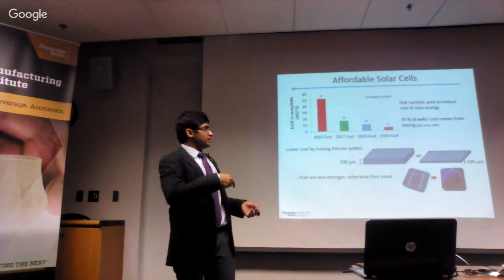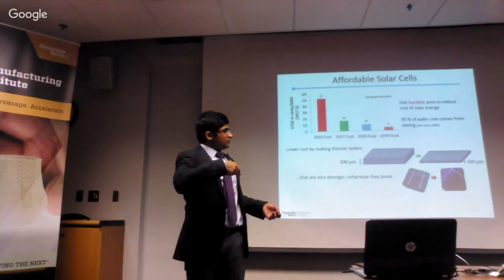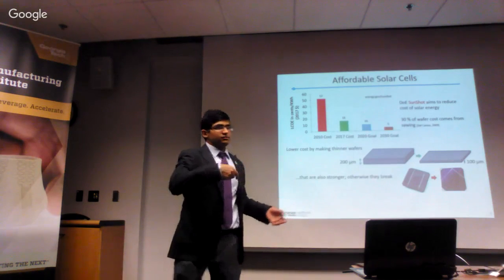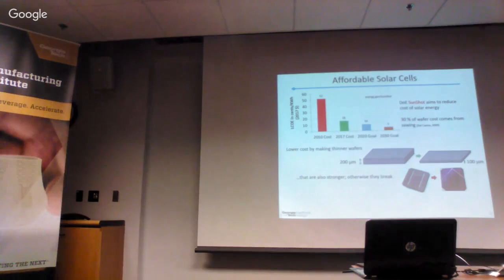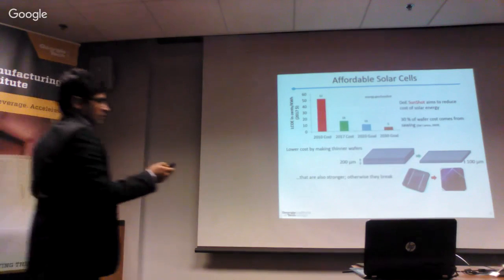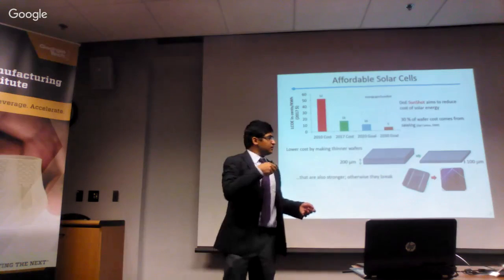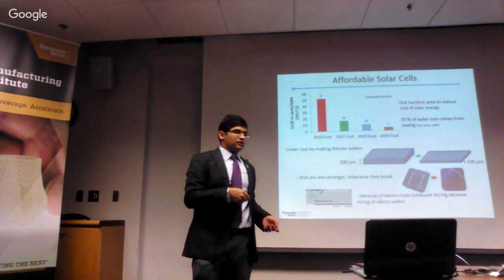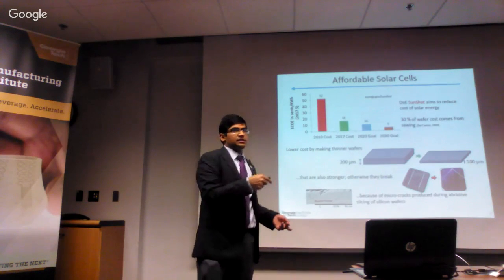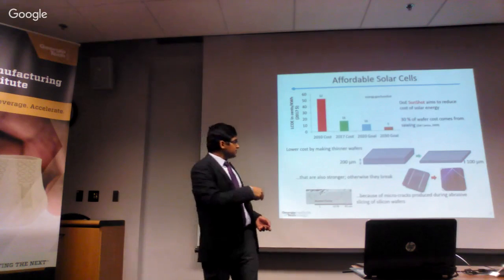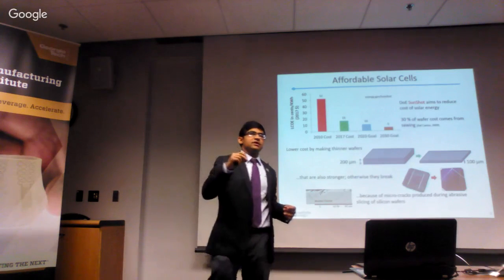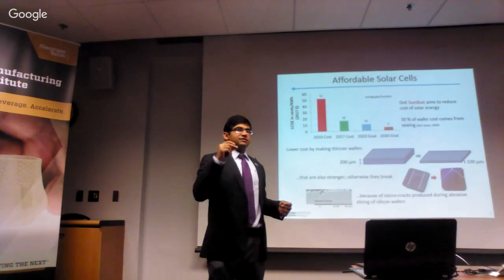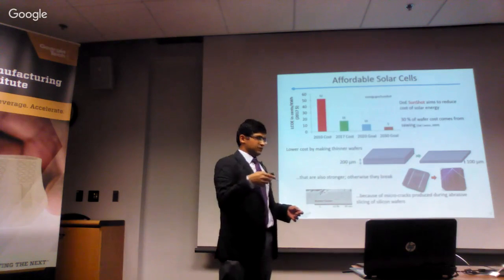Otherwise, the solar cells will break, as you see here. This is a complete solar cell, whereas this one is a broken one. And I'll pass out one complete solar cell, another broken one, for you to just look around. And these solar cells are breaking because of the micro cracks created in the surface and the subsurface of the silicon wafers, created during the abrasive slicing process of these wafers.